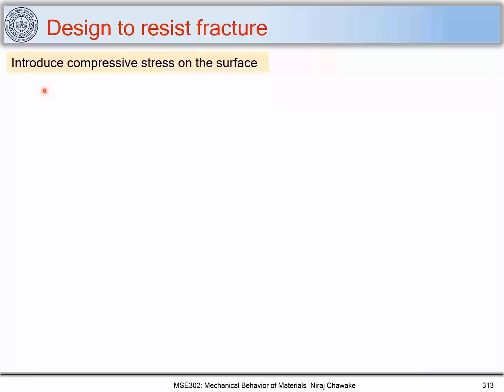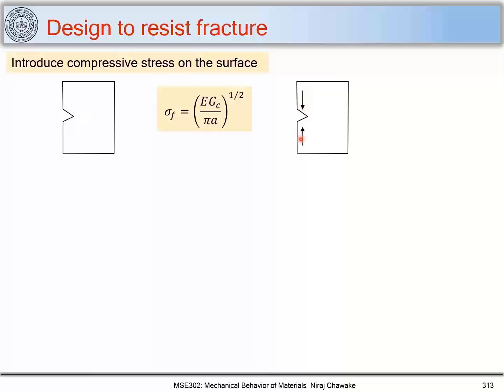Now another thing is you can increase the fracture resistance of a material by introducing a compressive stress on the surface. Let's understand this. We have this crack and we know that sigma f can be found out using this relation where a is nothing but the crack length. Let's say I have considered it as a surface crack. So what I do is put a compressive stress on this crack, and what it does is that the stress required to fracture, sigma f dash, will be sigma f plus this compressive stress, sigma compressive. This value will add up, and that is why you need more stress to fracture such a material which has compressive stresses on its surface.